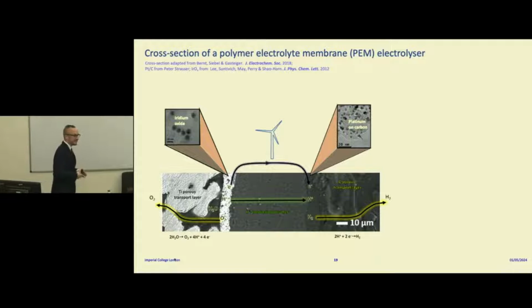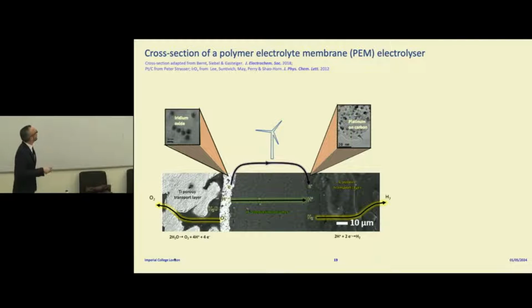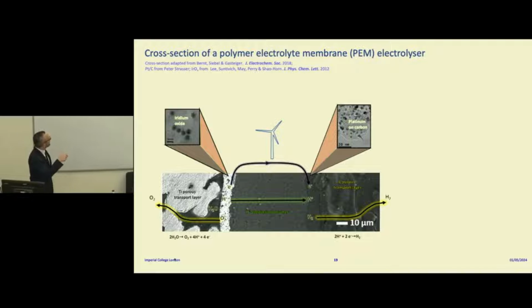An ideal way of testing different electrocatalysts would be to take an actual device and put it together. But you can imagine it's not that easy, because there are a lot of different steps to put it together. So it becomes difficult to see what the fundamental effect of changing the material is. Even if you look at these materials, you can see these platinum nanoparticles, the black dots, have a lot of different sizes and shapes, and each different size will have a different reactivity. So often what we do is look at more model systems and more model conditions, where we're just changing parameters more carefully.